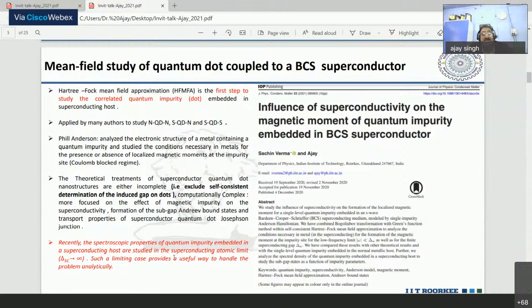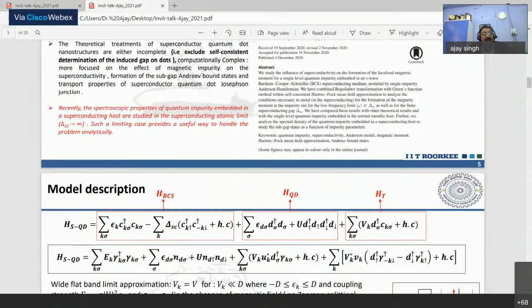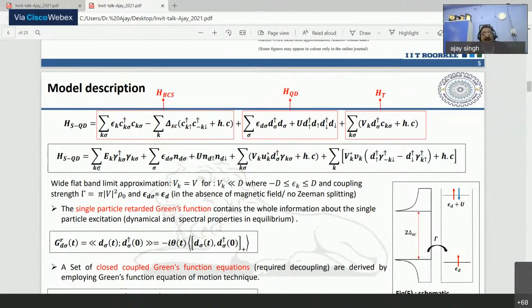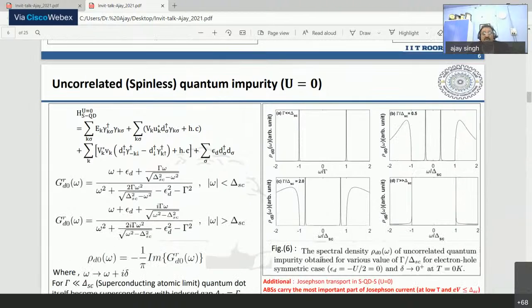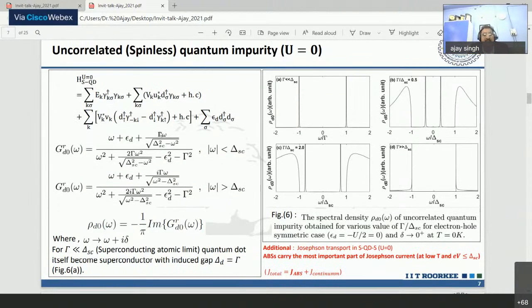And since there are experimental inputs, we initially started with a model which is just like your Anderson model coupled with a BCS lead, and we made a Bogoliubov transformation in order to bring the energy scales, you can say, to a level. We started with U equal to 0, and these results are obtained, which show that the density of states shows you the bound states within the gap region, and these bound states carry current. So you have a Josephson transport here in the U equal to 0 limit at low temperature. Total Josephson current has two components. One is the Andreev bound state plus the continuum.